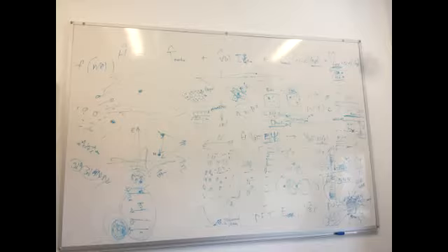And you can say, okay, this is larger than this, and the system will always try to get, not just try, everything aims to get to the lowest energy possible. So if there is such a configuration with lower energy, it will find it. So it basically means that experimentally you will find only this configuration. This configuration will never exist because it's higher in energy. So that's how you use these total energies to tell which configuration is more stable.